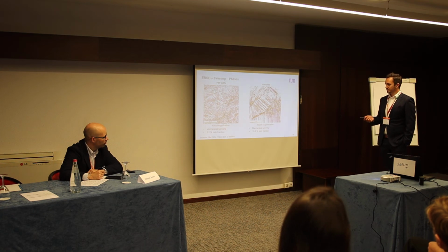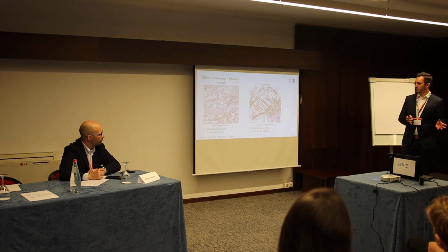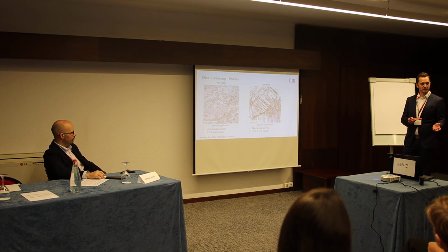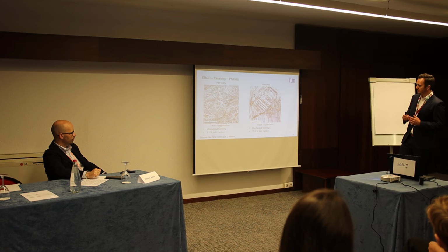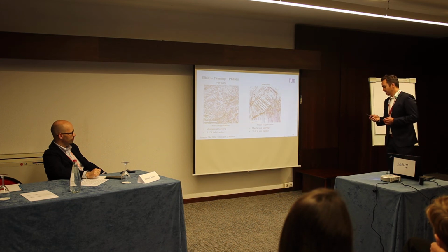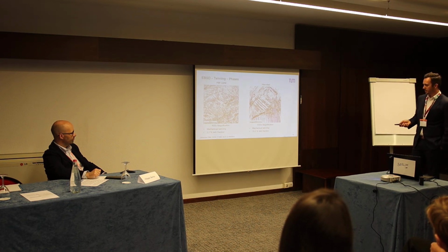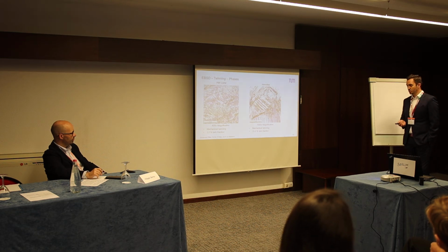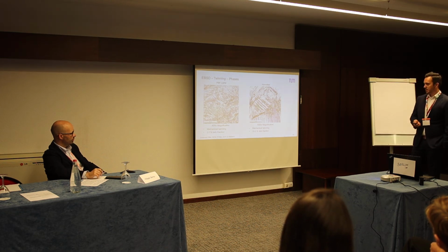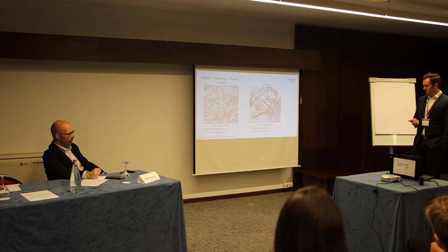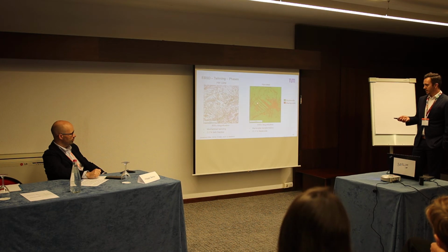So we have a little bit of mechanical twinning, which coincides with the results I showed earlier, that we have a very small amount of secondary hardening close before the end of the fatigue life. For the hot roll 316L, however, we can see a much larger twin fraction of 10.2%, so we have mechanical twinning. But we also investigated the crystal lattice structure with an EBSD measurement, and here we can see that we have also 11.5% martensite.